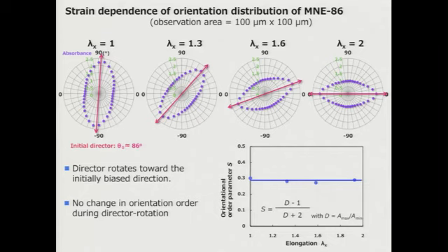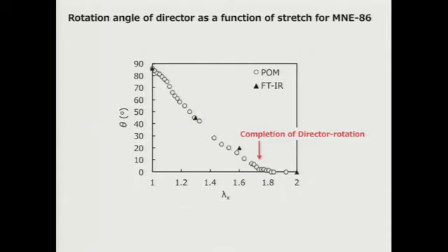Okay. So this figure shows the rotation angle of the director as a function of overall stretch. It looks like around 80% stretch, the director rotation is completed.